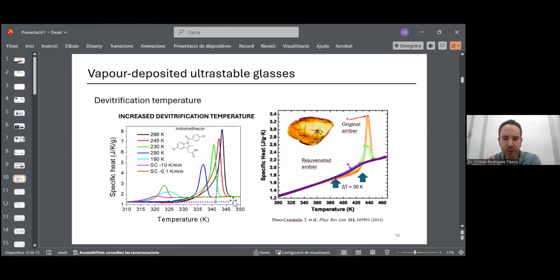With this, I want to say that by evaporating at the proper conditions, with physical vapor deposition, we can get glasses with a similar thermodynamic stability and a similar kinetic stability to those glasses that have been aged for millions of years, such as this amber. I'm not saying this is exactly the same because there are many differences in many properties, but from the point of view of kinetic and thermodynamic stability, these are very, very similar.